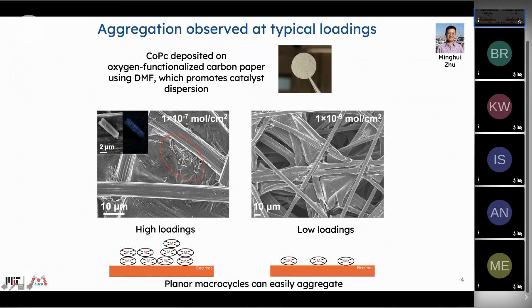So it turns out that this sort of crystallization and aggregation, even though it may overall lead to a good current density for the electrode, means that we're perhaps not getting maximum utilization of the catalyst. And so what we did then is simply dilute the catalyst and load it at a lower loading. And what we find is that at these lower loadings, these aggregates disappear. And this is something that's shown not just through the electron micrographs, but that one can also realize through kinetic analysis of these catalysts, that we can see now that these are in fact isolated sites. That's something that I'll show in just a few slides.